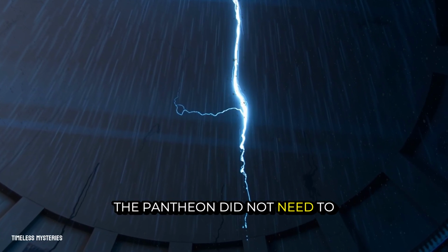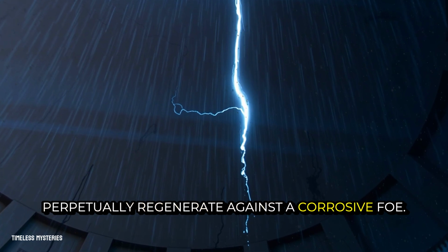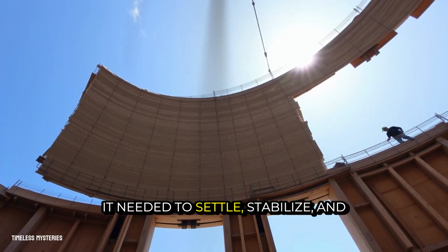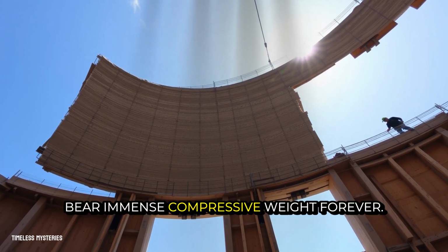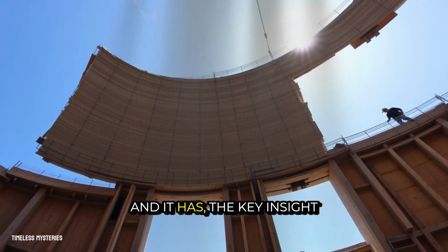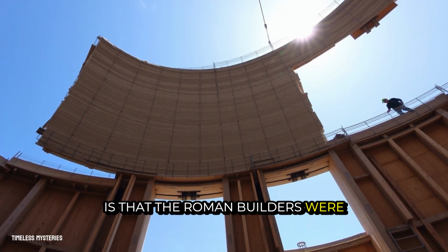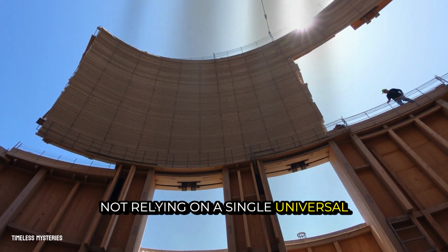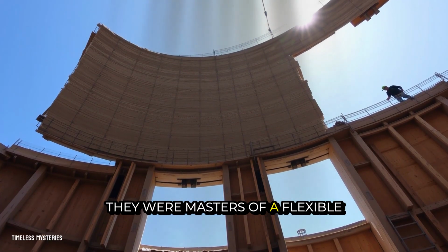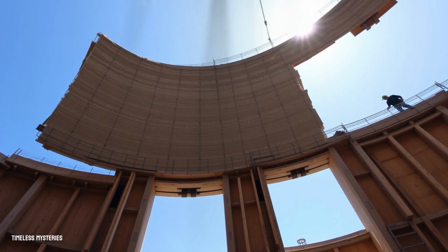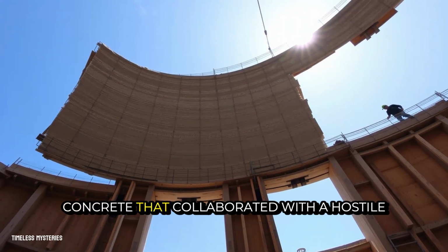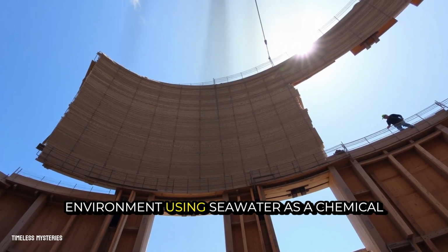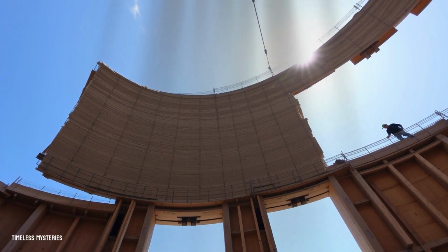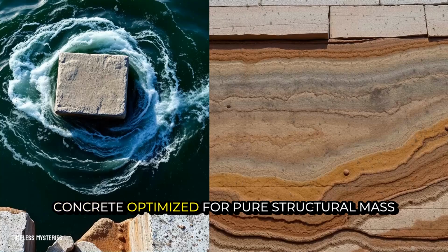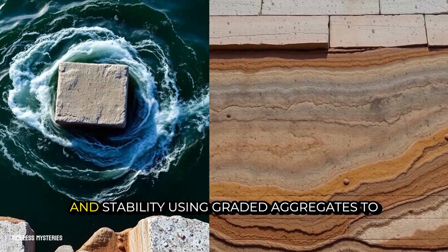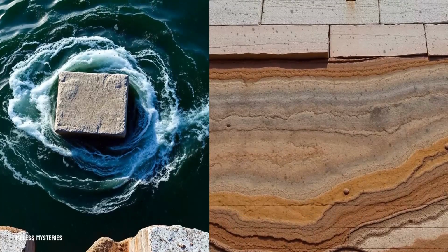The Pantheon did not need to perpetually regenerate against a corrosive foe. It needed to settle, stabilize, and bear immense compressive weight forever. And it has. The key insight is that the Roman builders were not relying on a single, universal concrete. They were masters of a flexible, adaptable technology. For the harbor, they designed a concrete that collaborated with a hostile environment, using seawater as a chemical partner. For the dome, they designed a concrete optimized for pure structural mass and stability, using graded aggregates to manage physical